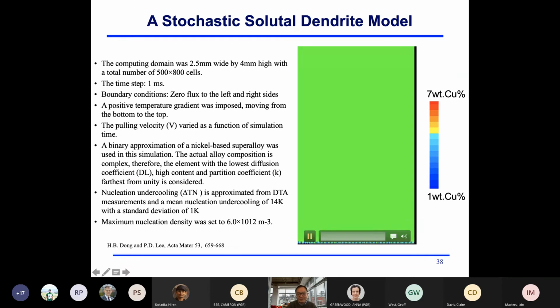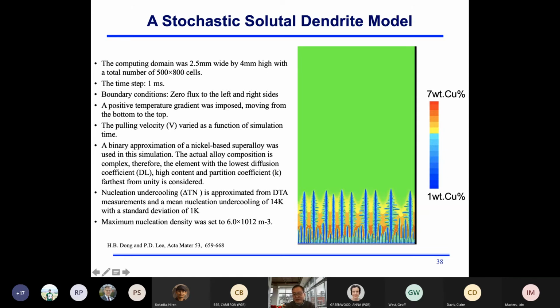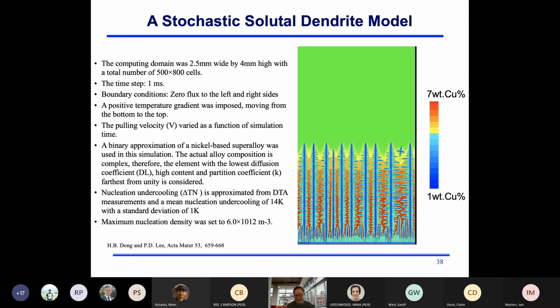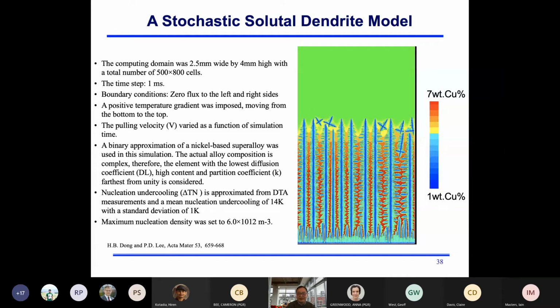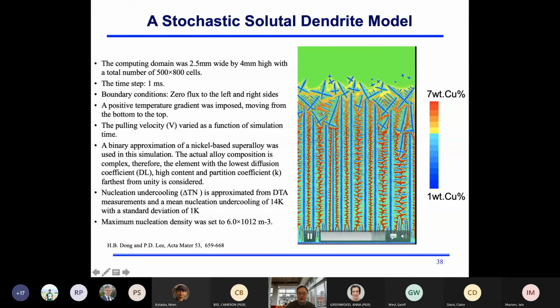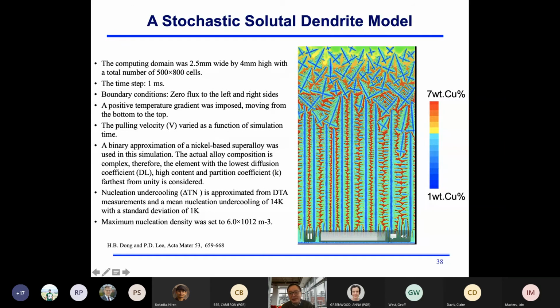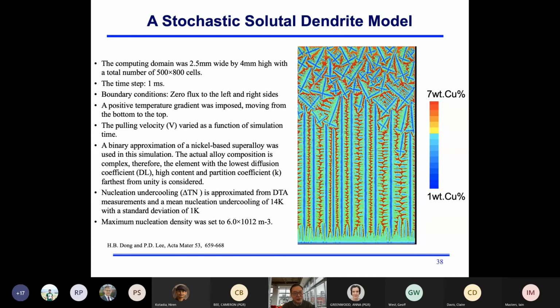Quickly show this movie. This is a movie we use, actually with aluminum copper as an example. This can be used to interpret other systems. A different color represents a different concentration level. The green one is a lower concentration, and the red color represents higher solid concentration. You can see how the concentration evolves during the solidification process. And then you will also see a columnar grain transform to an equiaxed grain. In this process, we try to mimic a welding process and reduce the thermal gradient. When you reduce the thermal gradient, you increase the possibility of forming new grains ahead of the grain front.